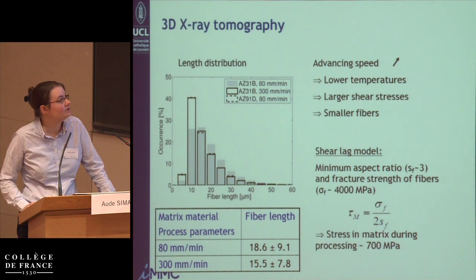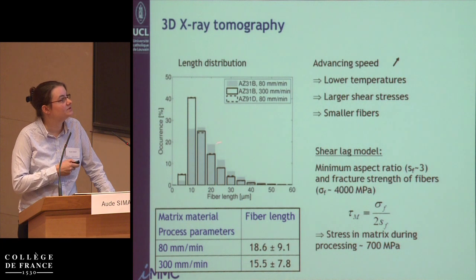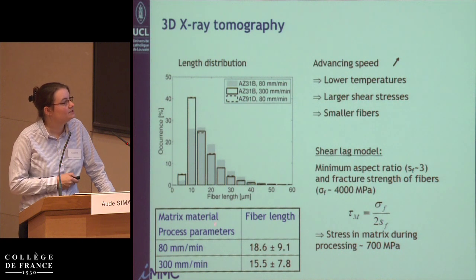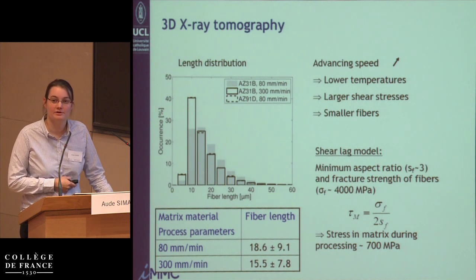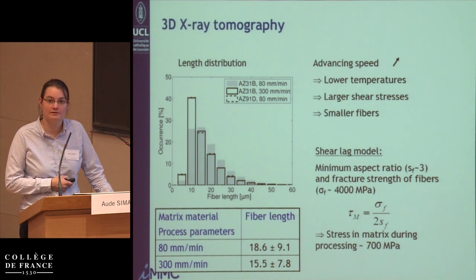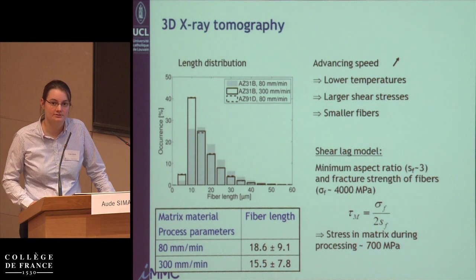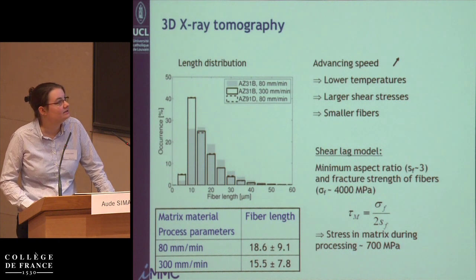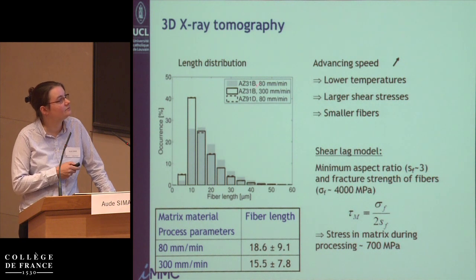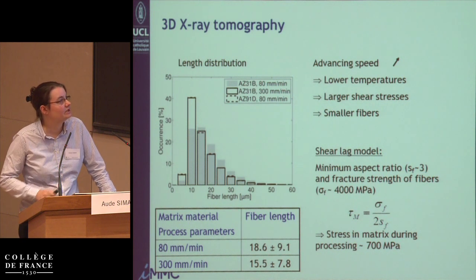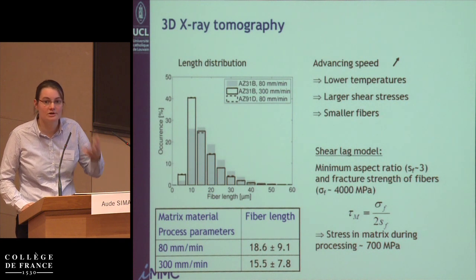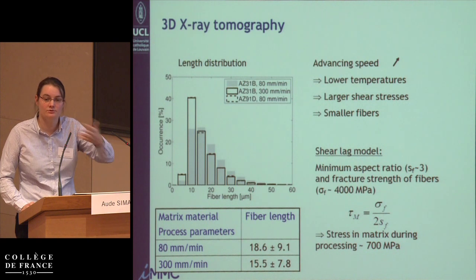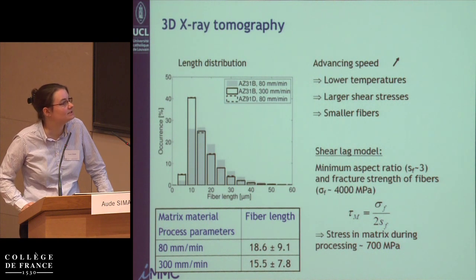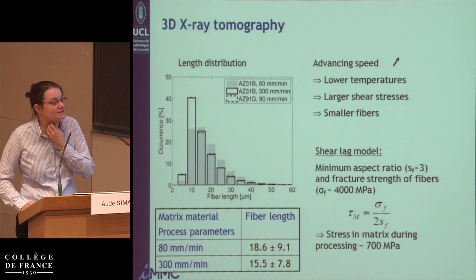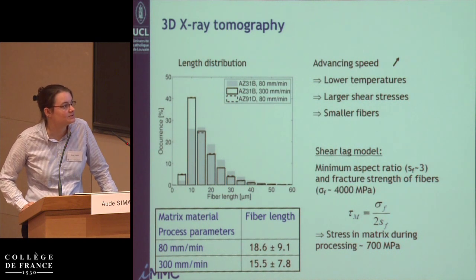And so here we have an effect of the processing parameters on the length distribution. And you see that these are rather short fibers. The ratio of their length to their diameter is about 3, so they're not very long fibers. And as the advancing speed increases here from 80 millimeters a minute to 300 millimeters a minute, well, you have lower temperatures because you go faster, so you heat for a smaller time. So you have larger shear stresses, and hence you end up with smaller fibers.